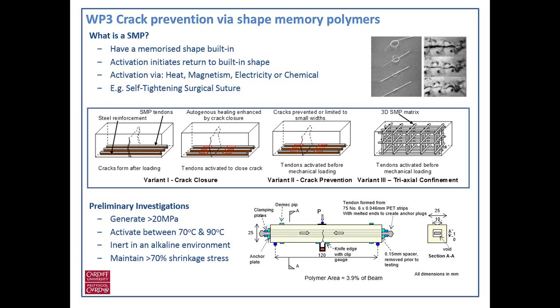As part of that, what we're doing at Cardiff University, and the research I'm personally involved in, is a crack prevention system using shape memory polymers. Shape memory polymers are being widely used within the medical, biomedical industry, also aerospace, but not so much within construction. They are polymers which are processed in a way to give them these shape memory properties. So they're essentially drawn at higher temperatures, around 80 degrees, well, it can be any temperature, what we're looking at is around 80 degrees, and then cooled in a restrained position, which then locks in this temporary shape. When they're then reheated, they retract back to their original shape.